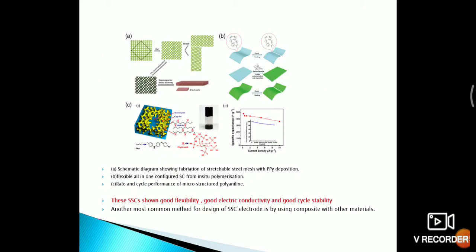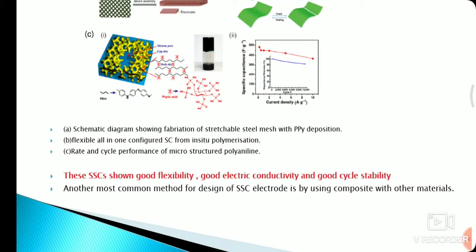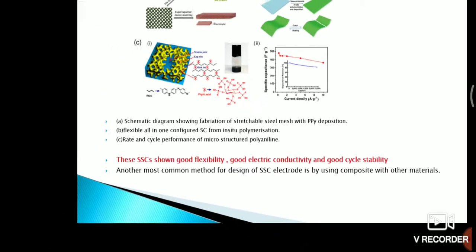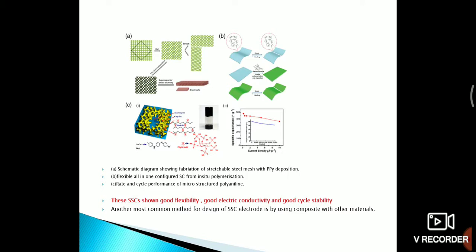This schematic diagram shows the fabrication of stretchable steel mesh with polypyrrole deposition. That is, here stretchable steel mesh is used as the substrate. And the second figure, figure B, shows the flexible all-in-one configured supercapacitor. And this shows the specific capacitance, the rate and cycle performance of microstructured polyaniline. This shows a high specific capacitance and also a high cycle stability. These supercapacitors show good flexibility, good electrical conductivity, and good cycle stability. And another most common method for the design of stretchable supercapacitors is by using composites with other materials.